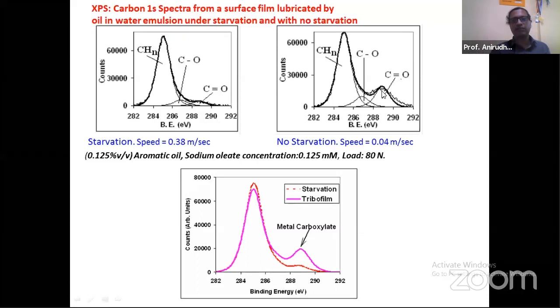Now, if you see this difference, because we should know that this is an oil in water emulsion, you can see that what is conspicuous in the case when it is well lubricated is the presence of a C double bonded O peak, which is on the right hand side. That means the presence of a carbon double bonded O formation in the case of a well lubricated film, which is evident from our XPS data, while it is not so when there is starvation, because it shows very poor formation of C double bonded O structures there.